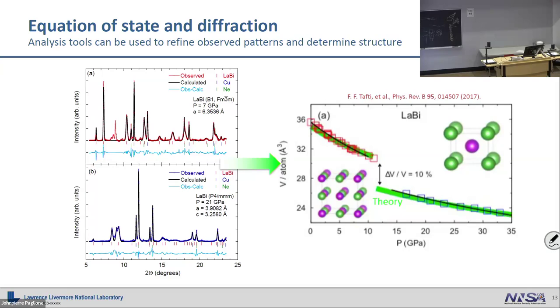Once you do that, you kind of know what your profiles look like, you understand your resolutions, and you can go through and do Rietveld refinement, Le Bail refinement, whatever you'd like to do to pull out X-ray diffraction data. And you can pull out lattice parameters, volumes, et cetera. In this case, this is some work we did many years ago now on lanthanum bismuth, looking at a volume collapse transition that's a kind of classic B1, B2 transition. So it's basically a salt to a salt kind of structure. And it matches really well with theory, which is maybe not surprising with something like lanthanum bismuth. But this is the type of data that you can pretty routinely get out. And nowadays, really, you could collect all of that data in a matter of hours or something like that, taking much longer to prepare DACs and to analyze it, but that's what you'd get.